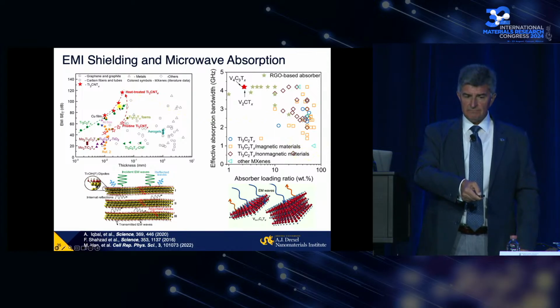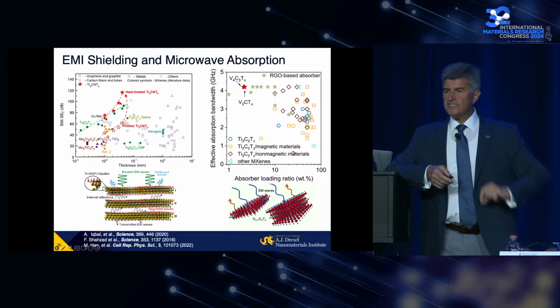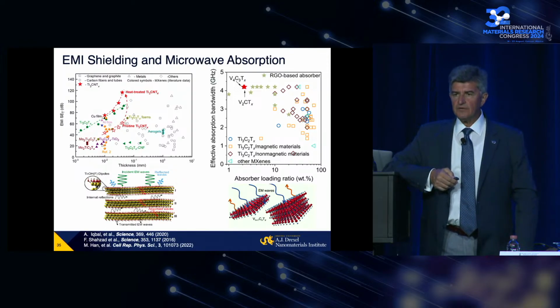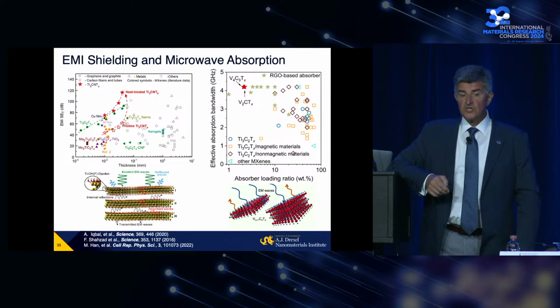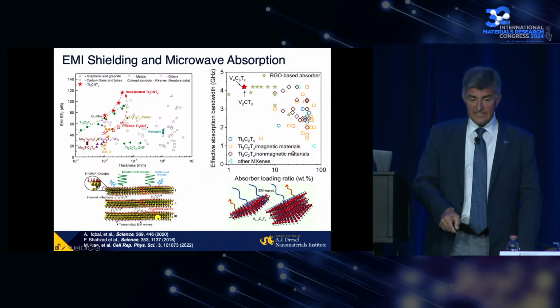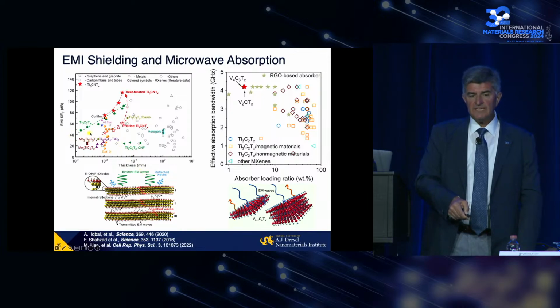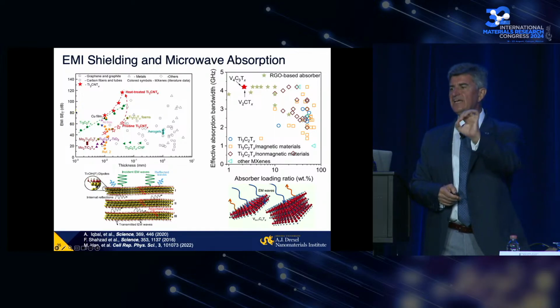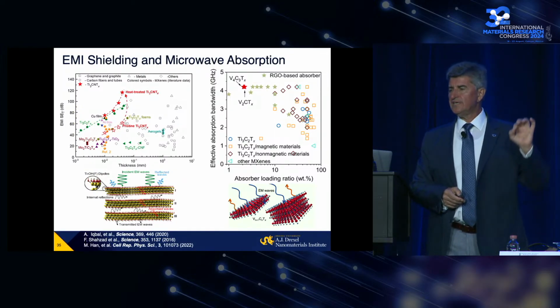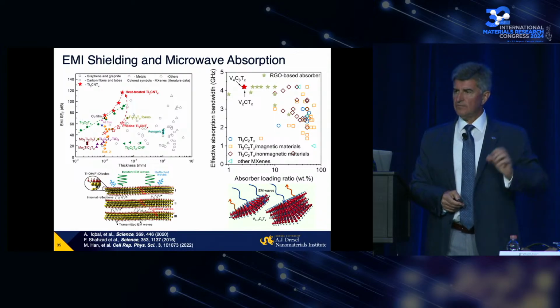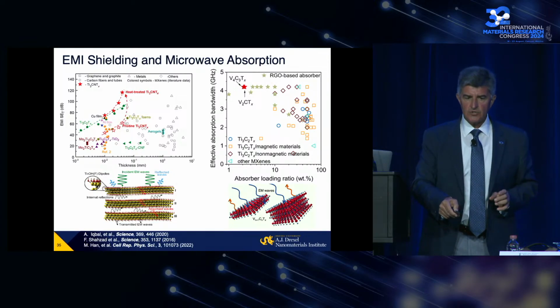Those are the same 10-micron foils, actually thicker, probably about 50 to 100 microns, in your cell phone for shielding. In 2016, we published a paper with Professor Chong-Min Koo showing that titanium carbide MXene aligns with copper and aluminum in its ability to provide EMI shielding. 50 decibels means 99.999% of all signal shielded. 20 decibels, on a logarithmic scale, means 99% signal shielded - enough for most everyday applications.